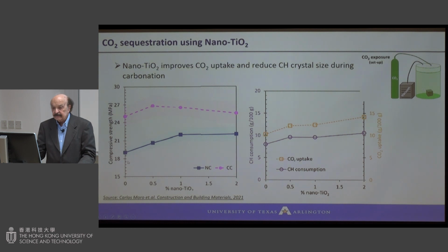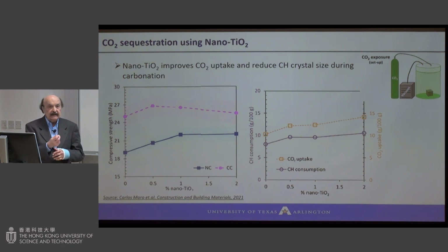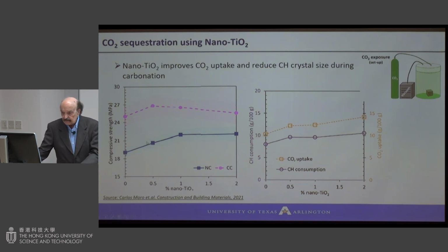what they found out is the addition of nanoparticles and compressive strength. Up to about 1% non-carbonated, compressive strength increases, and people attribute that to the nucleation effect of hydration of the nanoparticle. This has been done. But now when you carbonate it, with an addition of 0.5%, you increase quite a bit the compressive strength compared to control.